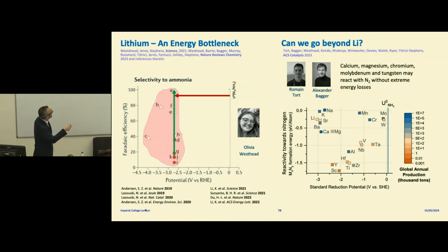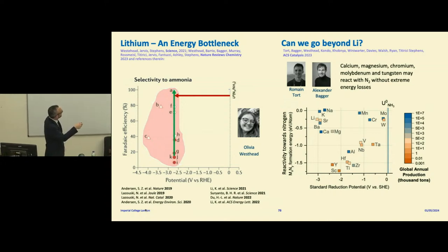So here's the reactivity towards nitrogen as a function of the reduction potential, how easy it is to make a metal out of these salts. Lithium is the most extreme here, and that's why it's good as a battery. But it turns out a lot of other materials, like calcium or magnesium, even chromium, molybdenum and tungsten, could in principle work a lot better, and they're very reactive towards nitrogen. So we thought, okay, let's try some of these. Actually, they didn't work, the ones we tried.